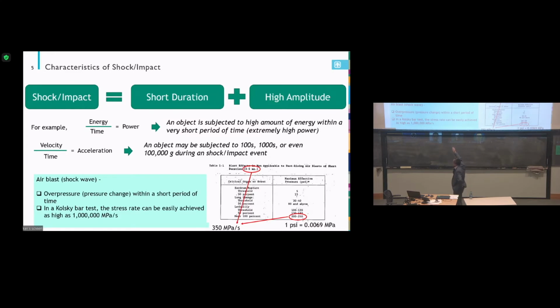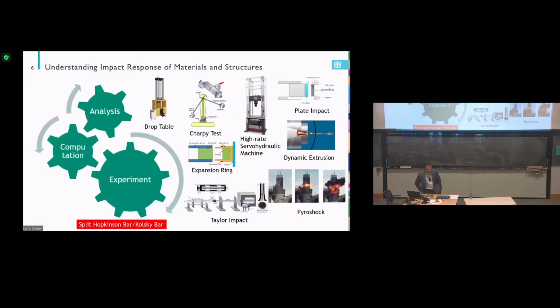However, what we are talking about in our lab, for example a Kolsky bar, I'll explain what a Kolsky bar is, the stress rate we're looking at is like 1 million megapascal per second. That's almost 3000 times higher than this. That's why we create a very extreme environment. Now, how can we understand the material response under this environment? You can do experiments, simulation, computation, even some kind of analysis. Here are some general experimental techniques we can use to characterize material response under different loading speeds, from very low, like MTS, to faster, like a high rate servo hydraulic machine, plate impact, dynamic extrusion, pyroshock, Taylor impact, all these dynamic events.